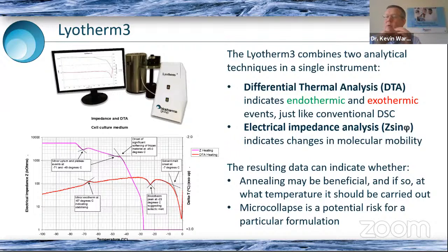Now, outwardly, we might then have a product which looks like a very nice freeze-dried product, but if we looked at it under the microscope, we would find that the cake might be collapsed, dense, and harboring moisture. So this might be something that we need to address for complex formulations. And this type of analysis is a classic example of something which can indicate when one phase is becoming softer, even if the other one doesn't seem to be changing visibly.